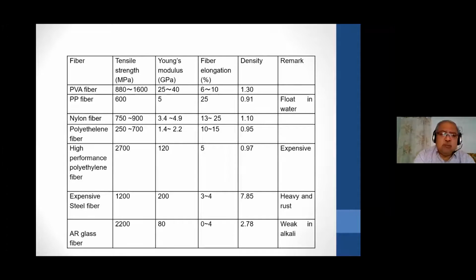We tested so many fibers before accepting PVA fibers as the best suited fibers for the FRC. We tested PVA, polypropylene, nylon, polyethylene, high performance polyethylene, expensive steel fibers, and AR glass fibers. Every fiber was tested in the laboratories for tensile strength, Young's modulus, elongation, density, and so many things. And then we found that the PVA fibers give us better results as compared to the others, because we could not take a chance in this mix design, because ultimately it was used for the monorail, where the structure is subjected to heavy static, dynamic, and rolling loads.